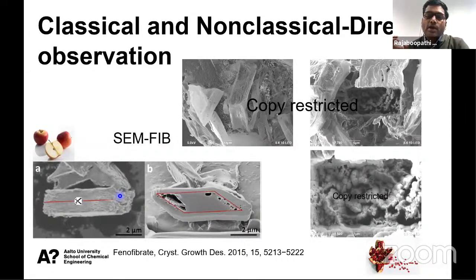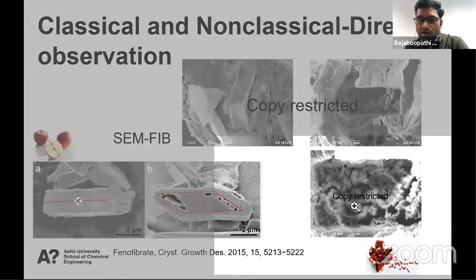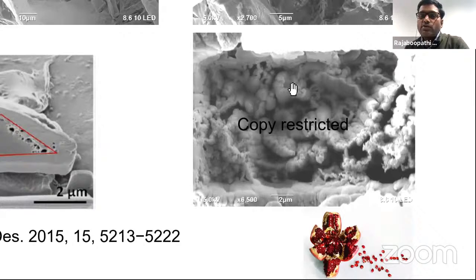Even though it looks like a mesocrystal, even though it looks like a hierarchical structure, after cutting the crystal, the cross section is completely single crystal. It is not made up of particle attachment. But in this case, this is another organic crystal, fenofibrate, where I used focused ion beam to cut the crystal. The outer surface looks like mesocrystals, but we don't know what is happening inside, whether it is made up of attachment of particles or atom by atom addition. In order to confirm, I cut the crystal using focused ion beam where you can clearly see the nanoparticle attachment. So this is one unit. Attachment of particles, we can call it a mesocrystal.